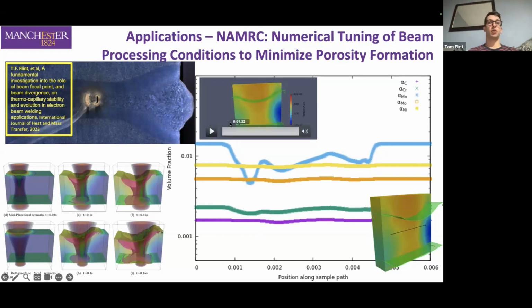Actually, what happens more often than not when that keyhole collapses is you get a lot of porosity, because either vapor porosity is included or gas porosity from the process. So we did some work with the NAMRC to try and numerically optimize, because an experimental campaign to find out the optimum parameters is prohibitively expensive.